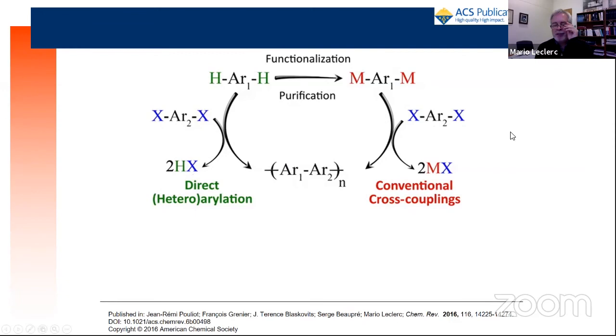conventional cross-coupling reaction where you have to activate, you have to make organometallic compounds, zinc, tin, or even boronic esters, and make a copolymerization with a brominated, most of the time brominated or iodinated, co-monomer to get these conjugated alternating copolymers, but you have a lot of waste. In this case, you just have HBr, HI. There is some work from Christine, I think, and what is his name at California, Thompson, Barry Thompson, where he now makes what we call these oxidative